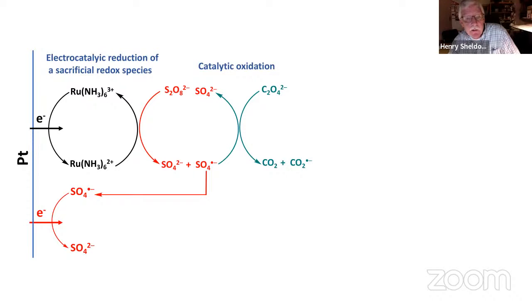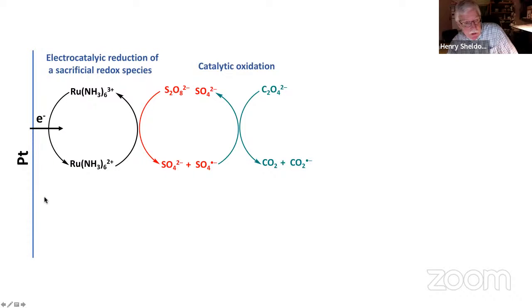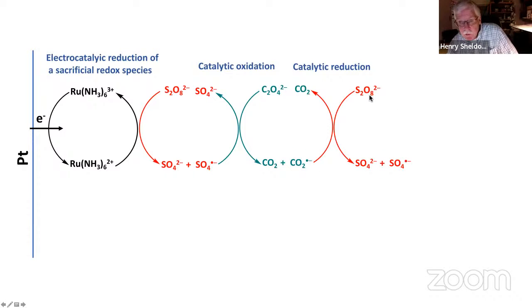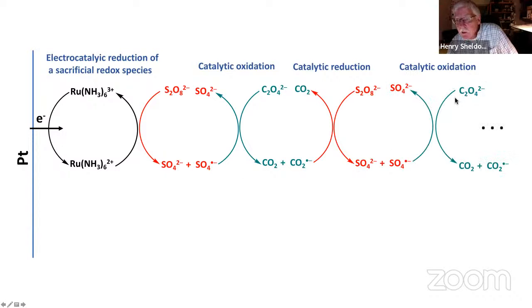But here, if you add another species to the solution, this is oxalate, what you can do is take this sulfate radical, and instead of it going back to the electrode, it can be used to oxidize oxalate to CO2 and CO2 radical anion. And so now the electron going into the persulfate is not coming from the electrode, it's coming from the oxalate ion. Now you've got CO2 radical anion. This is a super strong reductant, and it can reduce persulfate very rapidly, probably close to diffusion control rates. And now you generate another sulfate radical anion, same as over here, and it can now oxidize another molecule of oxalate.